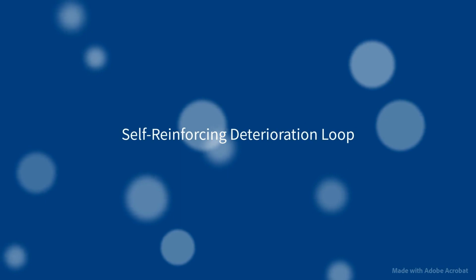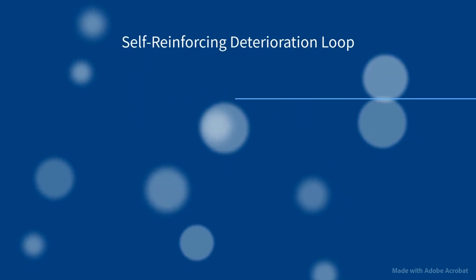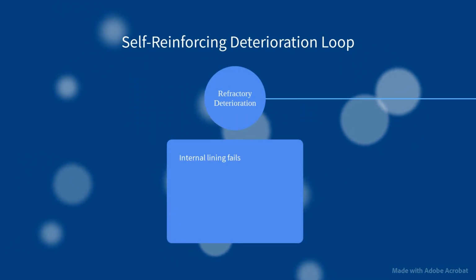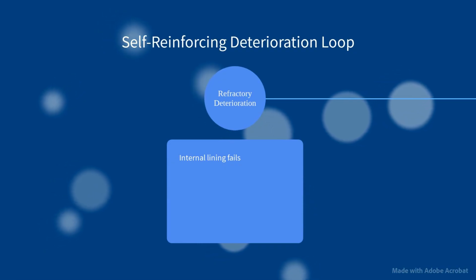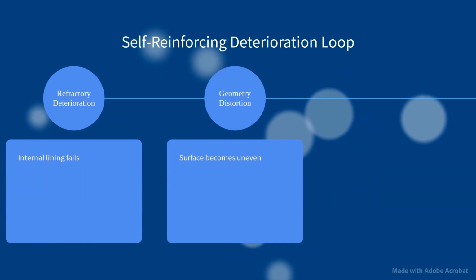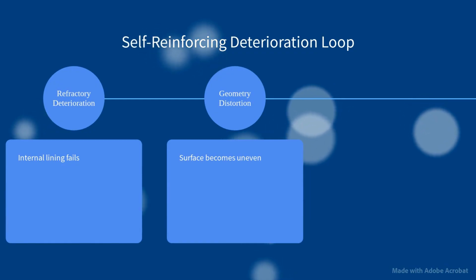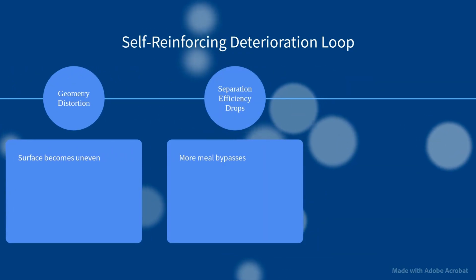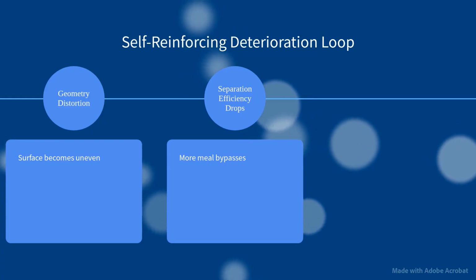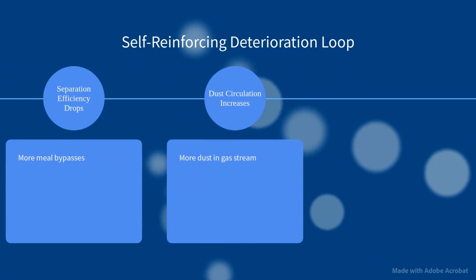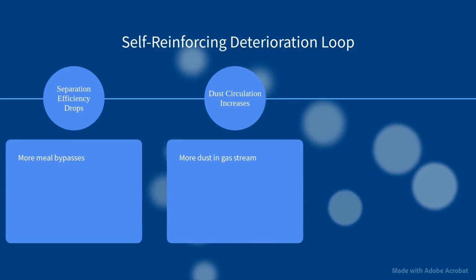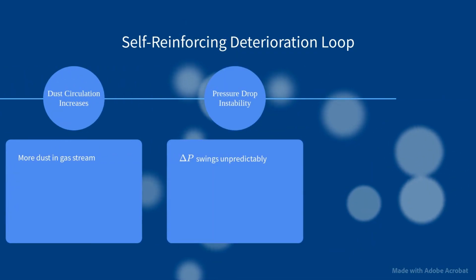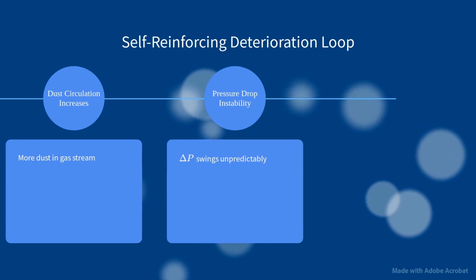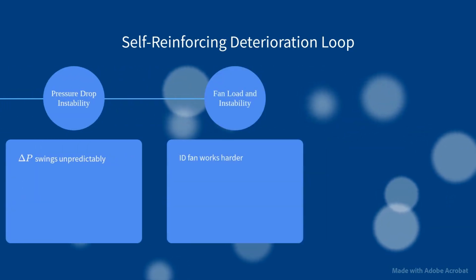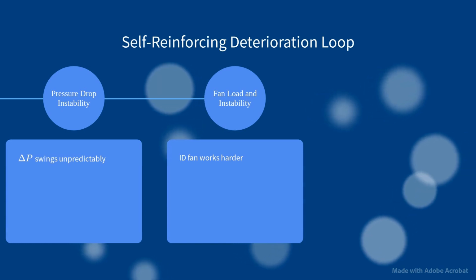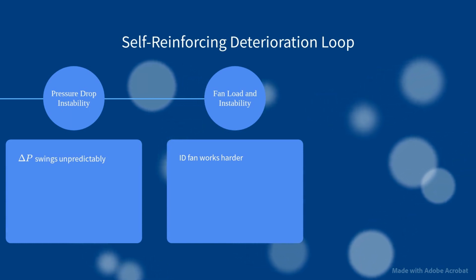Let's trace the chain of events that turn small internal changes into major process instability. Refractory deterioration is the starting point, as the internal lining begins to fail. Geometry distortion follows, with the cyclone surface becoming uneven and rough. As a result, separation efficiency drops and more meal particles bypass the intended path. Dust circulation increases, with more fine particles remaining suspended in the gas stream. This leads to pressure drop instability, where the pressure difference across the cyclone swings unpredictably. Finally, the ID fan must work harder to maintain draft, increasing electrical load and overall process instability.